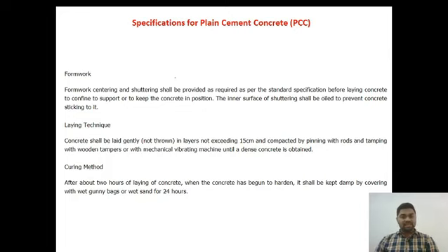Laying technique. Concrete shall be laid gently, not thrown, in layers not exceeding 15 centimeter and compacted by pinning with rods and tamping with wooden tampers or with mechanical vibrators.